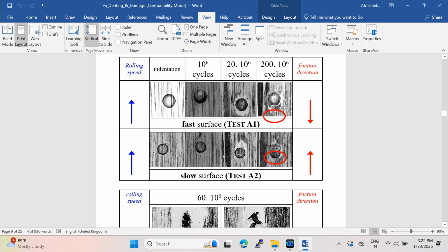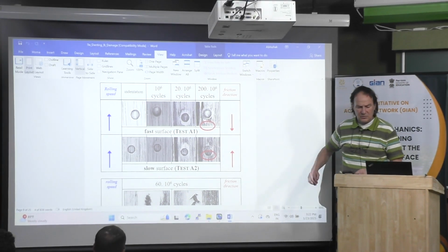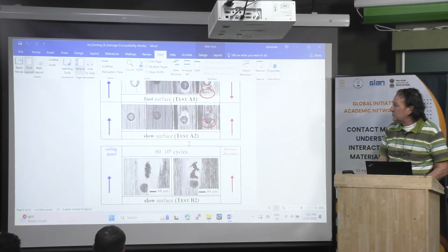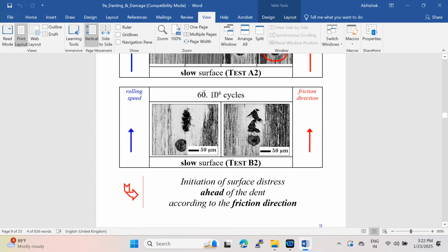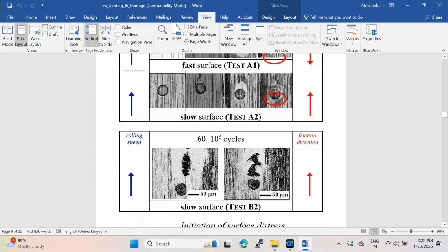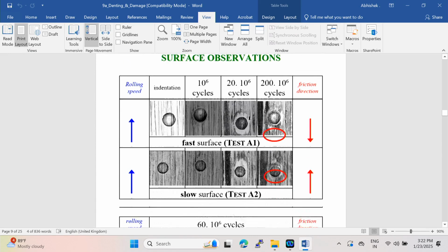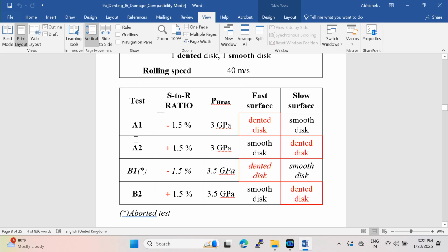Also, there is some damage ahead of the dent or behind the dent. It depends. And I think the circle does not correspond to the exact position. But you can see for the same dent, after 1 million cycles, 20 million, or 200 million cycles, how it evolves. I don't know here if it is pure rolling or not. Okay, this is pure rolling on the top. Test A1, A2, B1. The difference is the slide-to-roll ratio and the normal load.